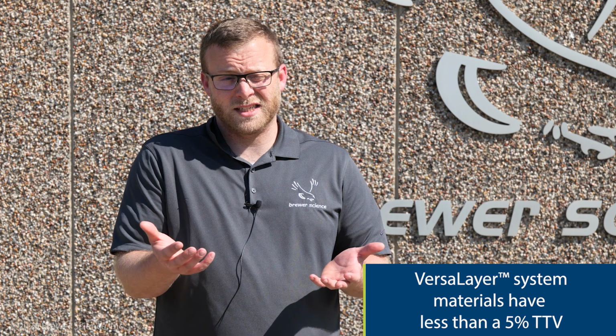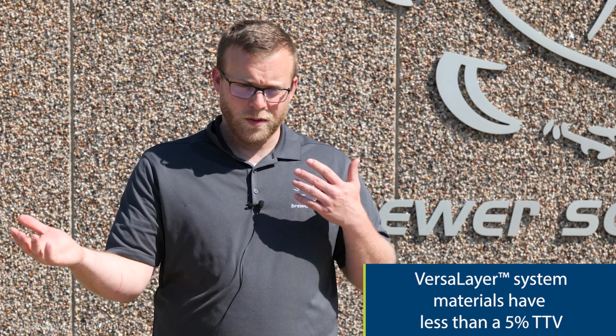Another thing we need to take into consideration is the total thickness variation of the wafer stack. For optimal performance, obviously, we want to keep that as low as possible. With our Versa layer materials, we've shown over and over again that we're able to get sub 5% TTV through the wafer processing. TTV less than 5% is important for stacking and adhesion. TTV that exceeds 5% can lead to uneven bonding, which eventually will result into loss of adhesion or delamination issues in the device.